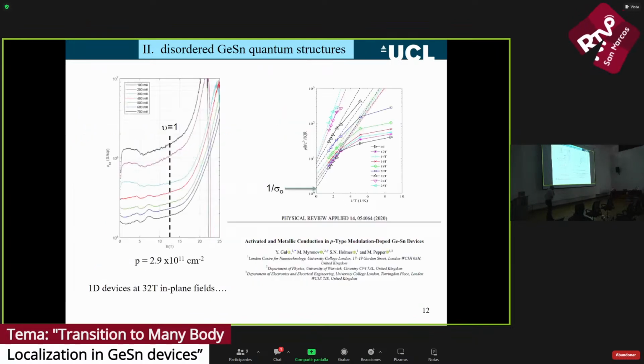What we also did as we were doing that work was we took some of the samples to Grenoble, where there's a high field magnet lab, where we had 32 Tesla at our disposal. So the question was, what happens at high fields? And interestingly enough, this is now resistivity, so ρxx as a function of magnetic field. We were going up to 30 Tesla, but the device we're measuring is 10 to the 6 ohms per square, 10 to the 7 ohms per square. And the device was about 10 squares. So we're measuring extremely high resistances here.